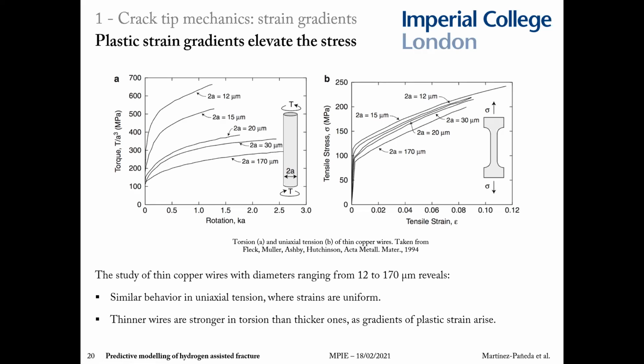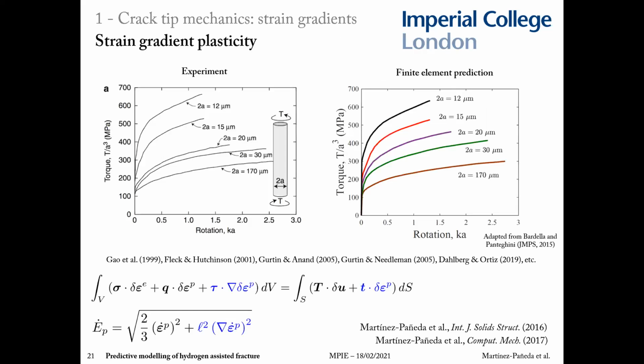Of course, if I were to try to capture this size effect using conventional plasticity models like von Mises plasticity, I wouldn't be able to do so because there's no length scale in the constitutive equations. But the good news is that many clever mechanicians, some of which are listed in the slide, have devoted their efforts to extend plasticity theory to small scales by developing what are called strain gradient plasticity formulations. The general idea in these formulations is that the plastic work or the flow strength is related not only to the plastic strains, but also to the plastic strain gradients. In that way, a length scale comes naturally into the model due to dimensional consistency.